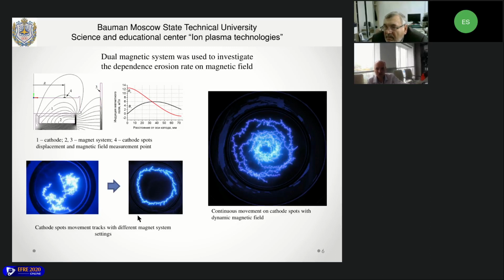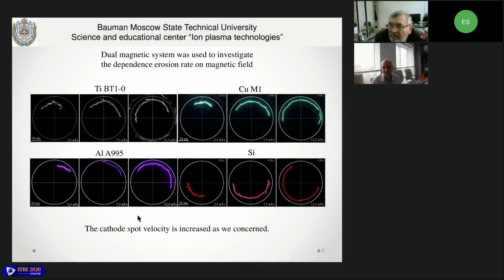So next, at first, I should note that in a magnetic field the velocity of the cathode spot is increased. The work was done for titanium, copper, aluminium, and silicon. I think this holds for all materials we can investigate. For all the materials, the velocity increases with increasing magnetic field. You can see this in the length of the cathode spot track.